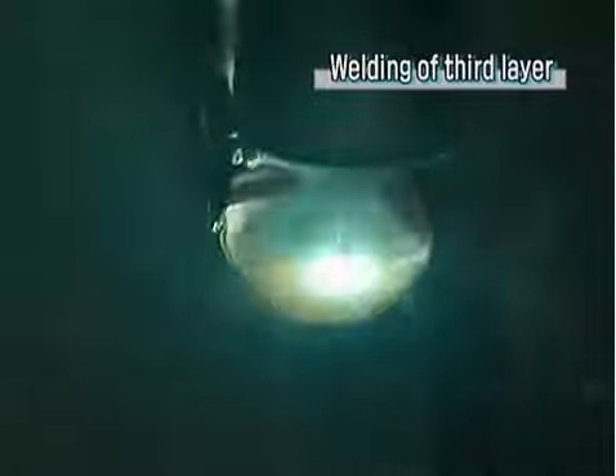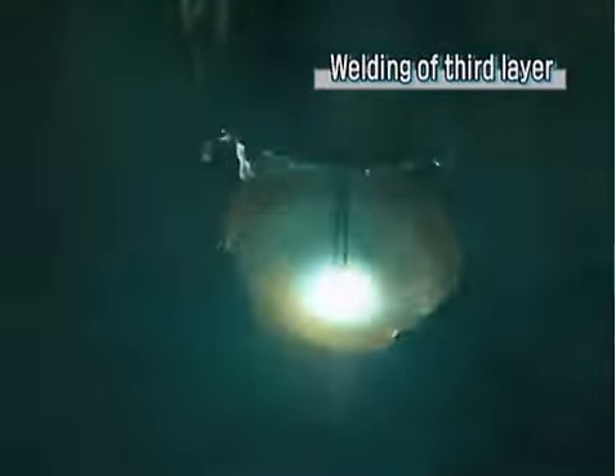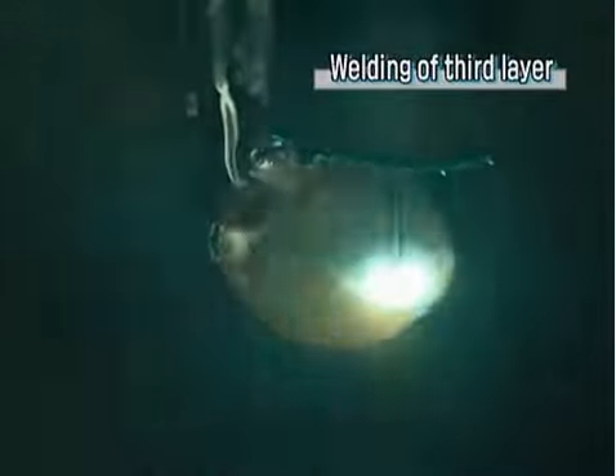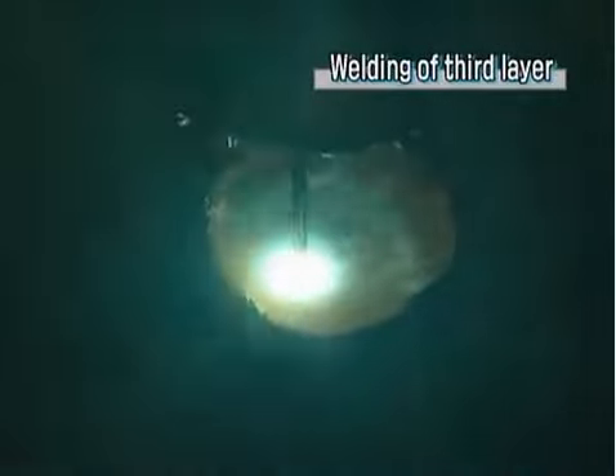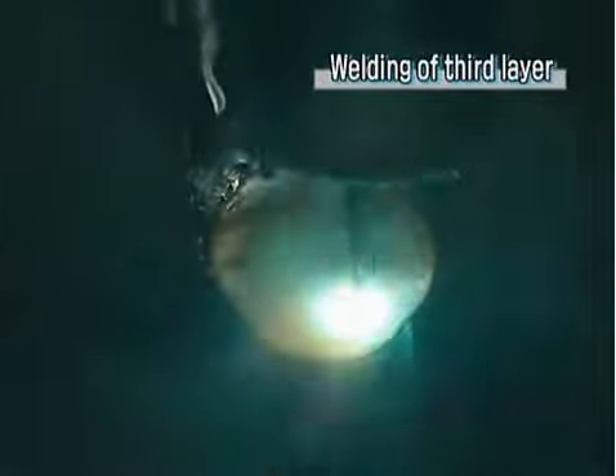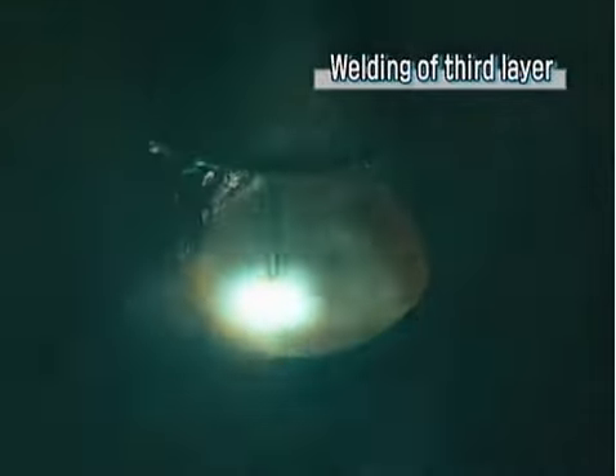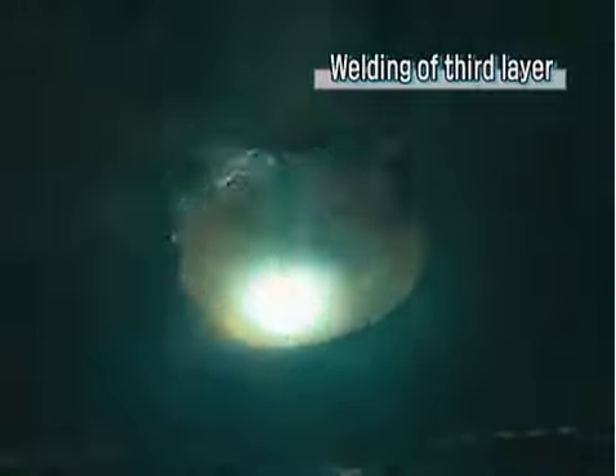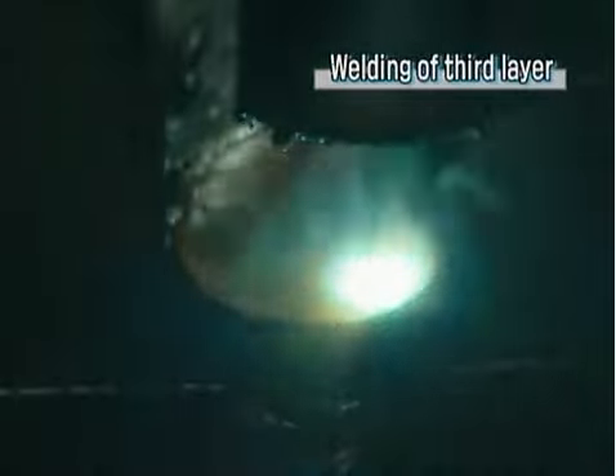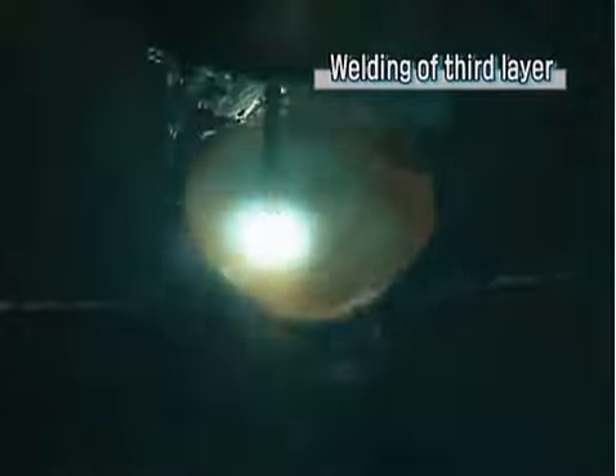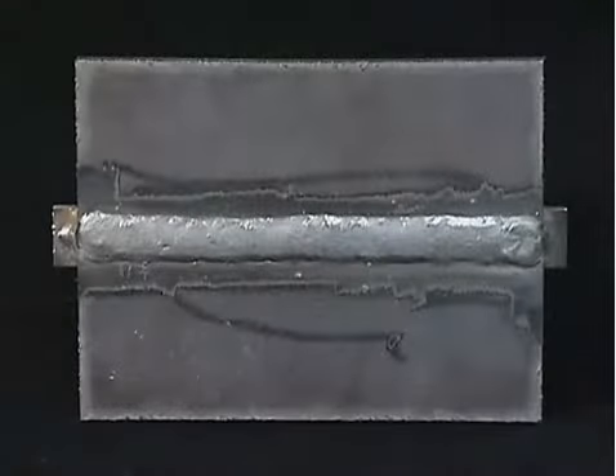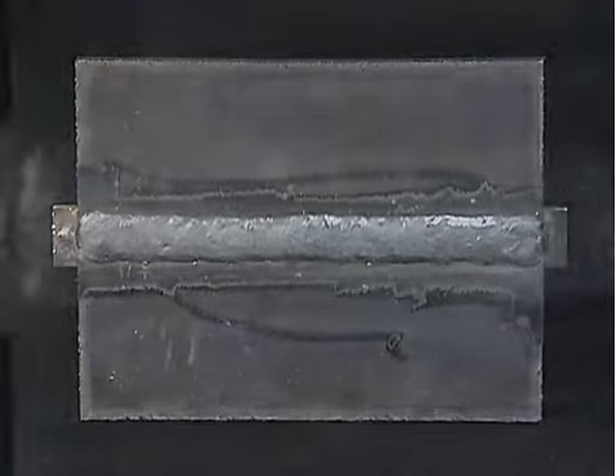To avoid undercuts on either side of the bead width, move the torch slowly. Weaving that extends beyond the groove width can cause uneven bead width, so be sure to stop before you reach the groove line and allow the spreading of the weld pool to melt the groove edge. At the finishing point, fill the crater and be careful to avoid burn-through or insufficient weld reinforcement height. This completes the job. Let's look at the weld now.